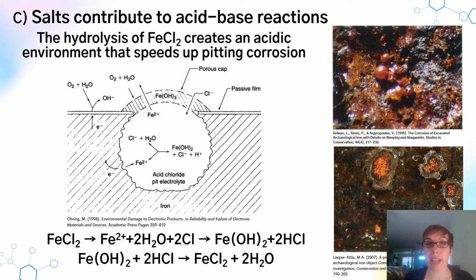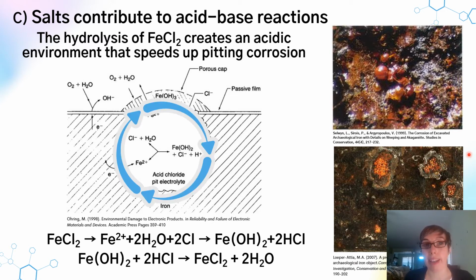Often this occurs in tandem with other types of corrosion activity, and what can happen is the formation of a corrosion blister on the surface of an artifact, just what you see here in this picture. This blister is comprised of a thin layer of oxidized iron corrosion and is filled with a ferrous chloride and water solution that quickly becomes acidic and forms a galvanic cell and quickly dissolves the underlying material, creating corrosion pits beneath the blisters. And what's more, this process is cyclical and self-perpetuating and can lead to massive material loss as these pits deepen.